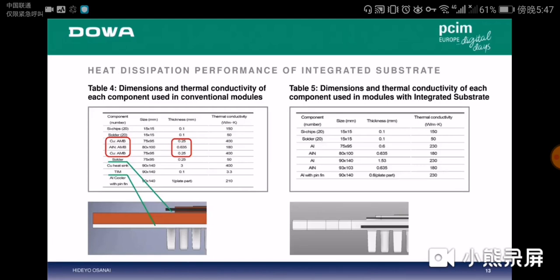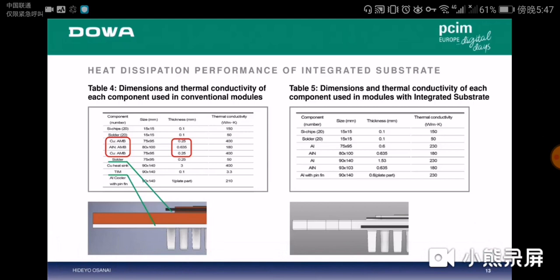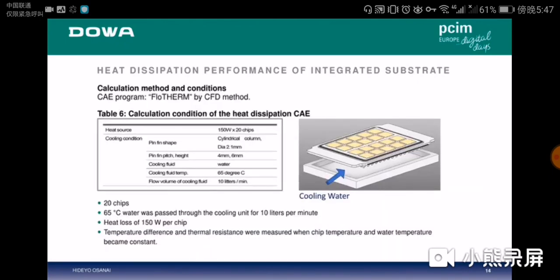Next, we evaluated the heat dissipation of the two-ceramics model against the conventional module structure by simulation. Table 4 shows the components of the conventional model structure with aluminum nitride substrate. Table 5 shows the module assembly with the two-ceramics integrated substrate. This sheet shows the applied CFD calculation method and conditions for determining the temperature difference between chip and cooling water and thermal resistance.